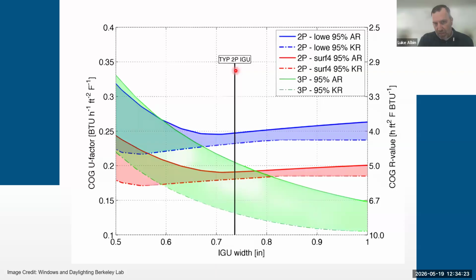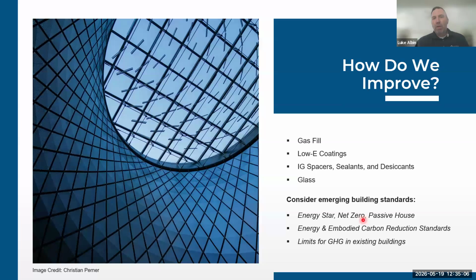You'll notice with this typical dual pane geometry, the performance pretty much flattens out at 3/4 of an inch. And actually, you tend to lose a little bit as that gap gets bigger. Whereas in the triple pane, or these green lines, you are still gaining thermal performance through an inch and even a little bit beyond, to about an inch and a quarter, inch and 3/8. So definitely a lot more potential with the triple pane from a thermal performance standpoint. So that's how we improve.